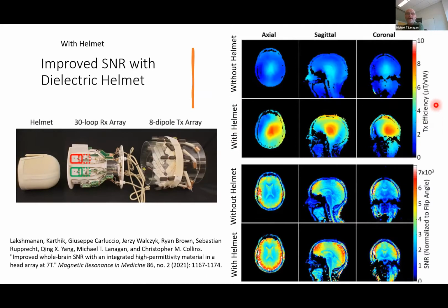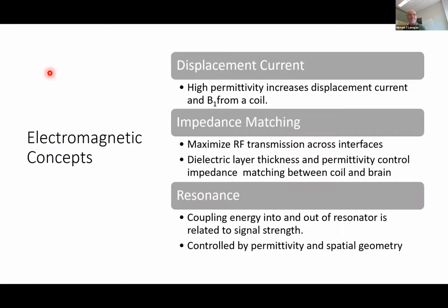And here we're looking at the transmit efficiency in terms of microtesla per square root watt produced. And we can see here that we can see an enhancement when we add the helmet to the array. But more importantly, we can see that we see an enhancement in the signal to noise ratio when we add it as well. So this shows some promising results, just very recent, on using these dielectric pads to couple the signal in and out. And then, of course, the really interesting part is, what's happening physically.